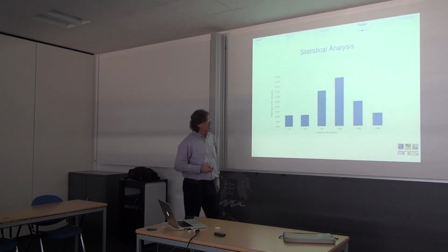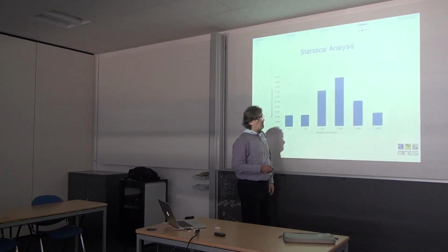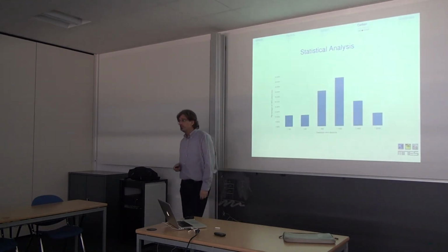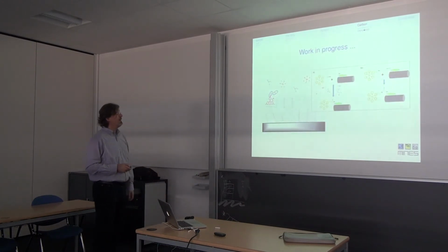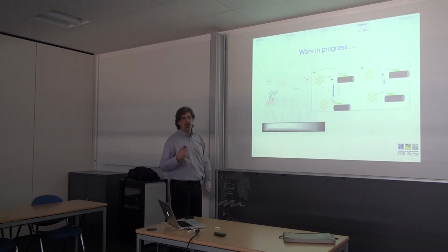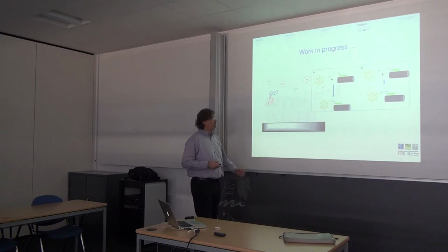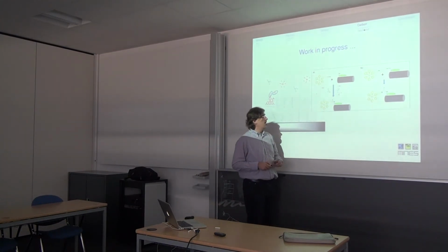In fact, doing the statistics, we arrived up to 1 to 2000 in terms of detection limit. And so now, talking about the biomedical application, I will show you some results of what we did and are doing, which is this.